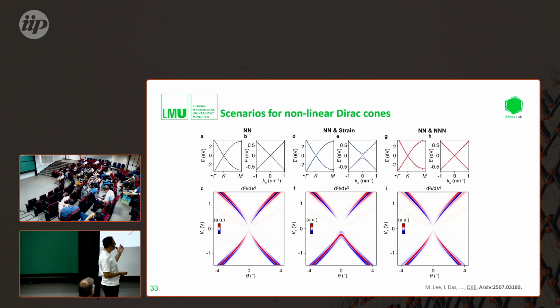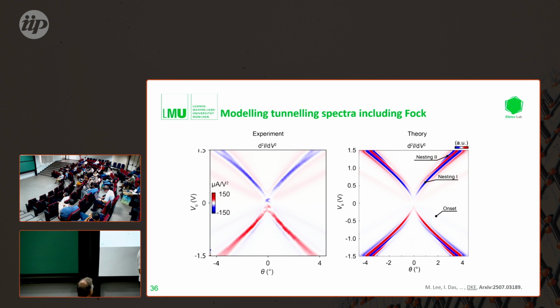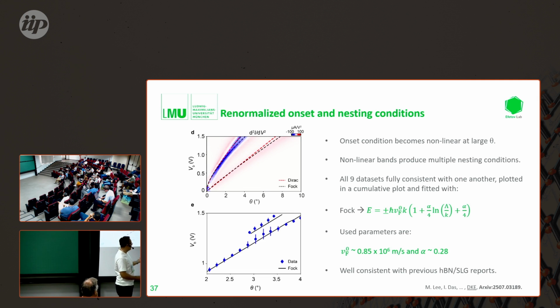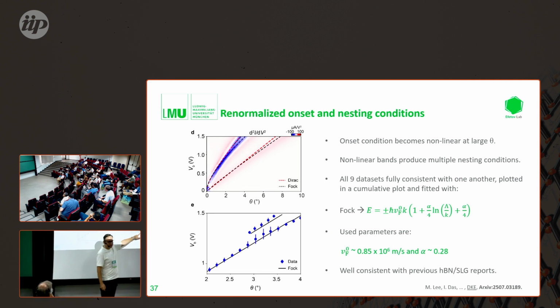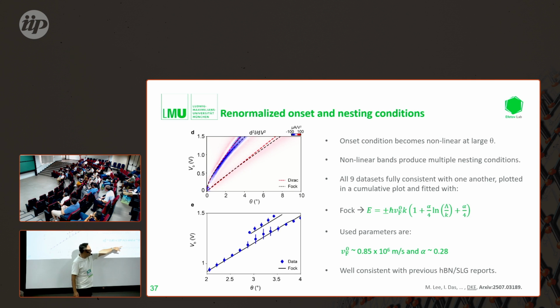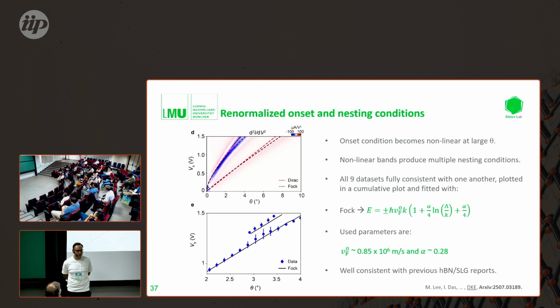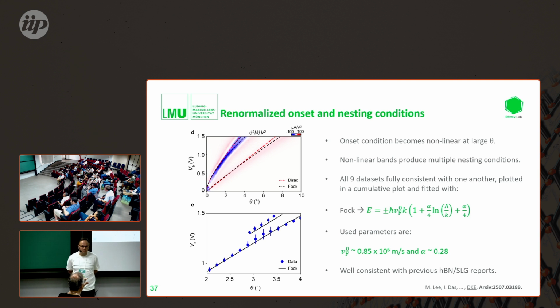In this calculation, one just basically assumes these parameters, alpha and Fermi velocity and lambda and whatever. And this is where this curvature gives you the right nesting. Then you can compare those parameters that we extract to literature values. What convinced me is that we really get the right literature values. We get 0.85 on the Fermi velocity and alpha of around 0.3, which is consistent with what people have reported before.